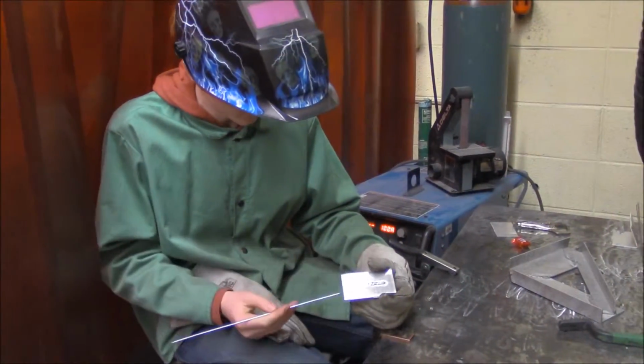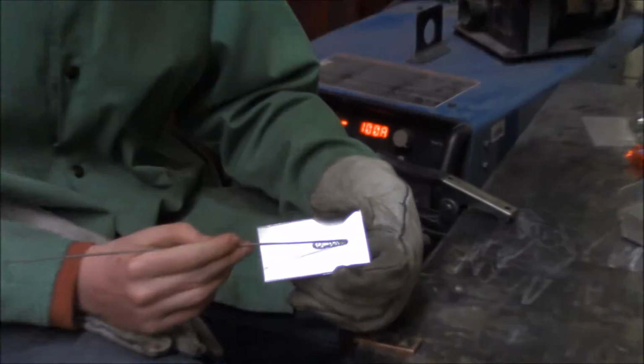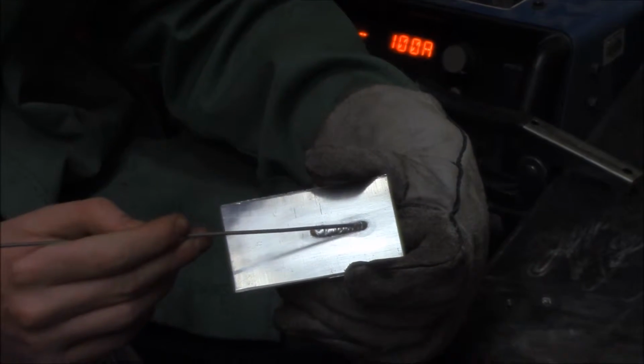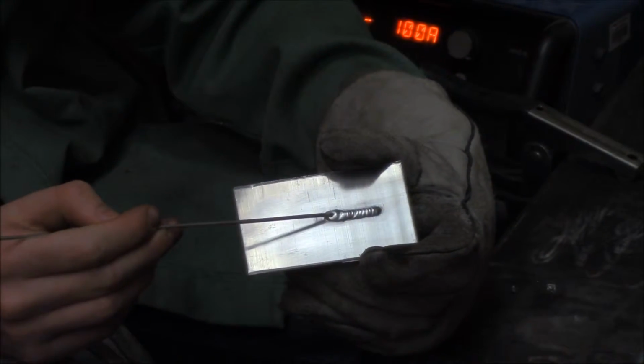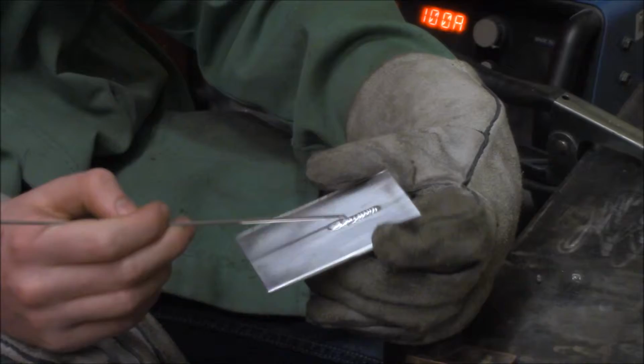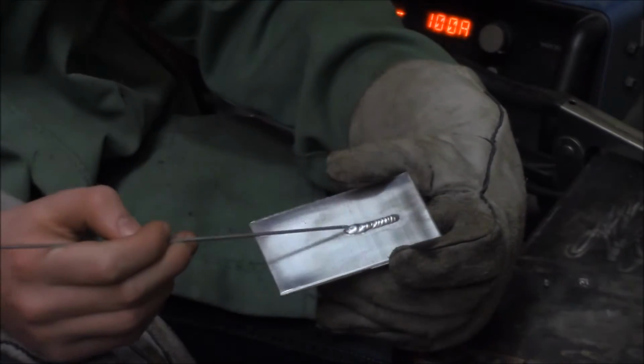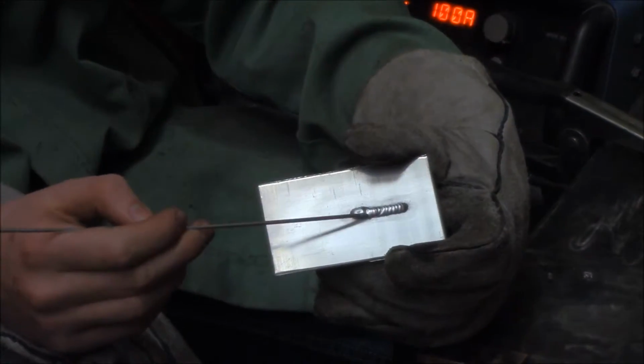Okay, so this is what your final weld should look like. It has an even height, even width, and each time you put in filler it's fairly even. This is a pretty good weld. It got a little big at the end because the metal was getting hot. But that's the basics when it comes to TIG welding.